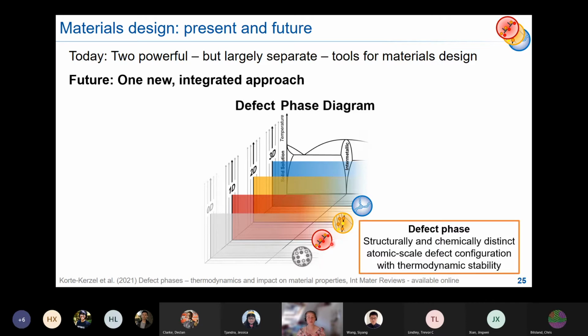So the first thing to get clear here is what we actually understand by a defect phase, so we can put them in something like a defect phase diagram. And we understand by this a structurally and chemically distinct atomic scale configuration at a defect that has a thermodynamic stability, so something that I can affect by changing the temperature, the chemistry of the alloy, and so forth.